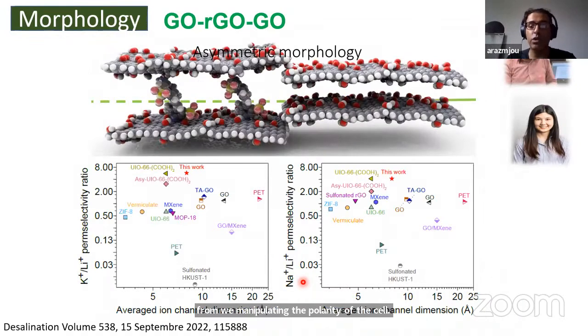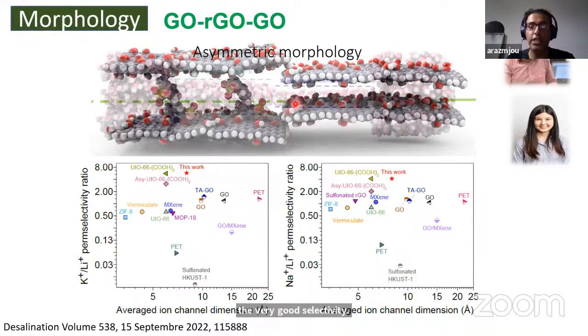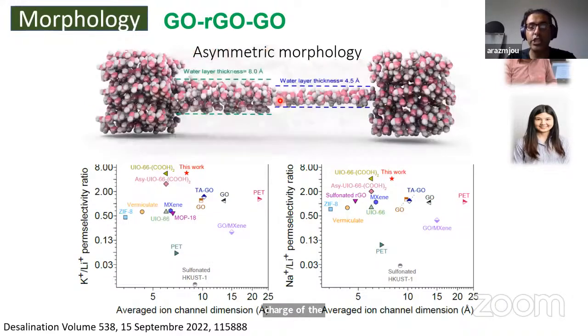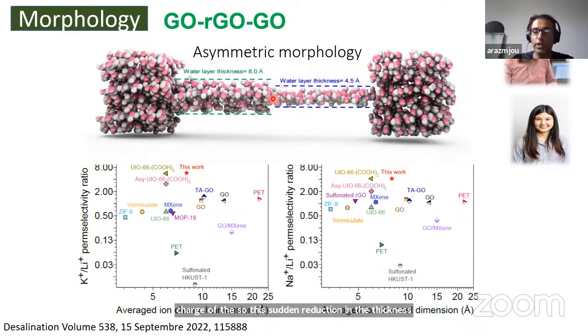We also managed to create asymmetry using graphene oxide membranes. As you can see, our membrane showed very good selectivity after creating a sudden reduction in the thickness of the graphene oxide. This sudden reduction provides a great opportunity to boost lithium ion selectivity.